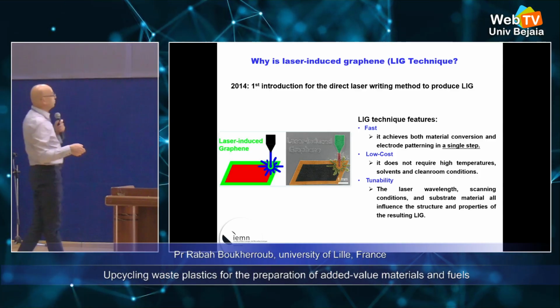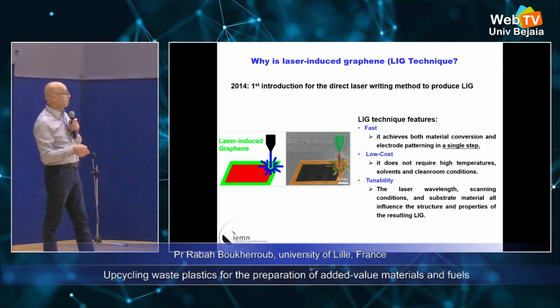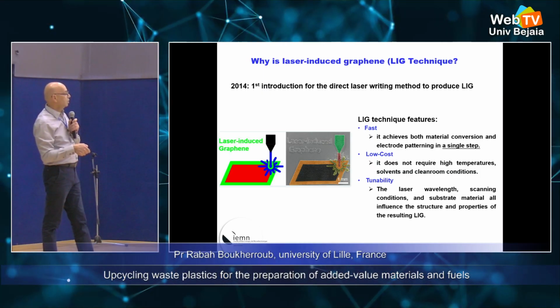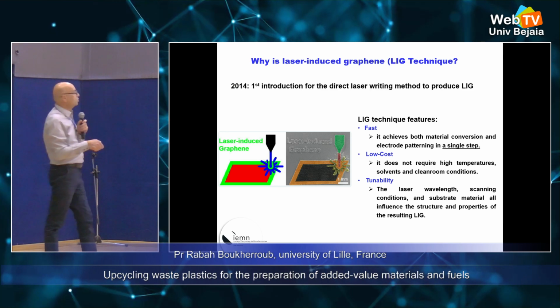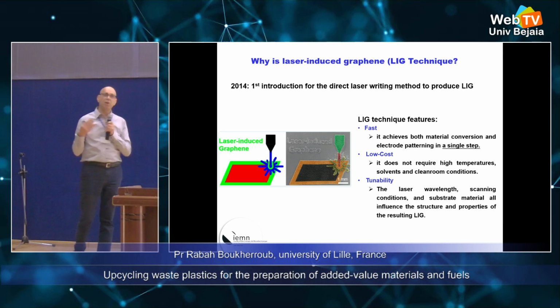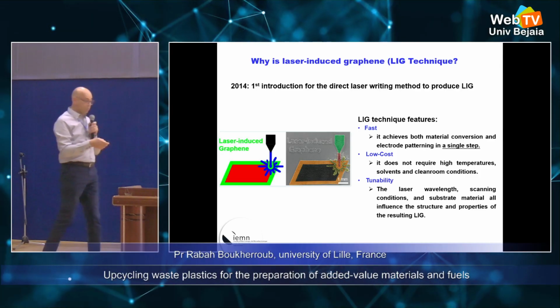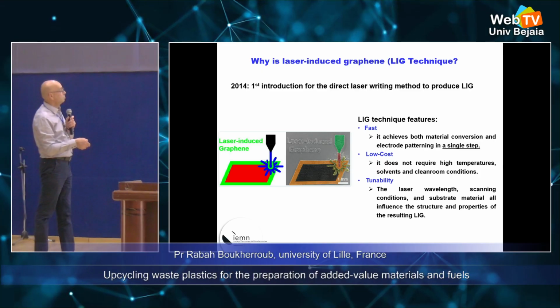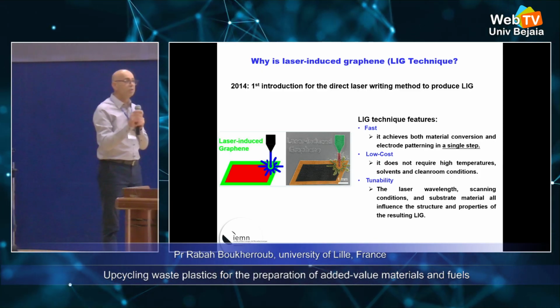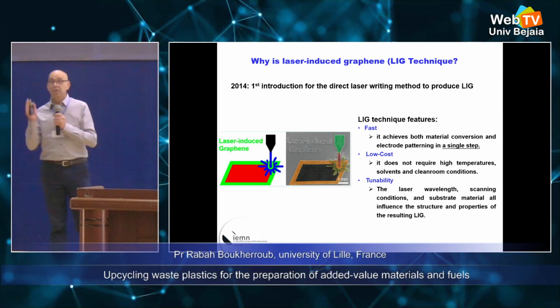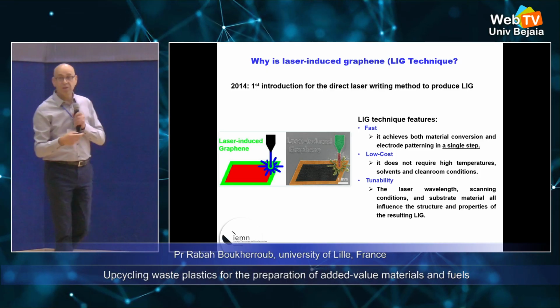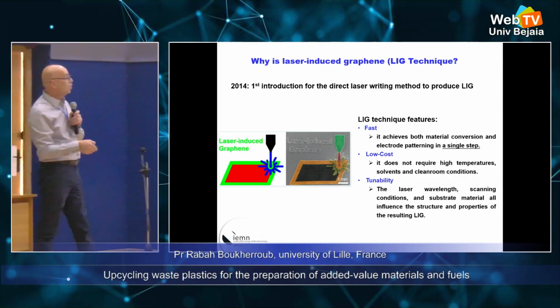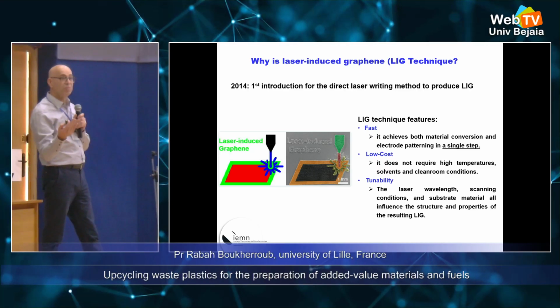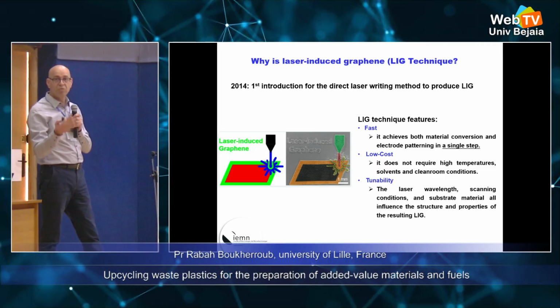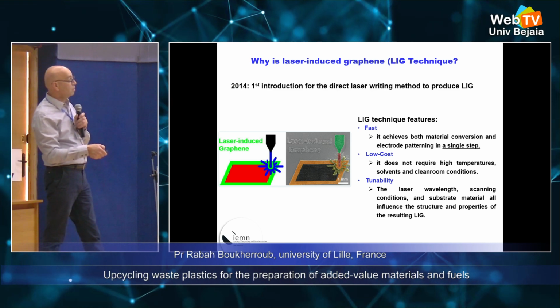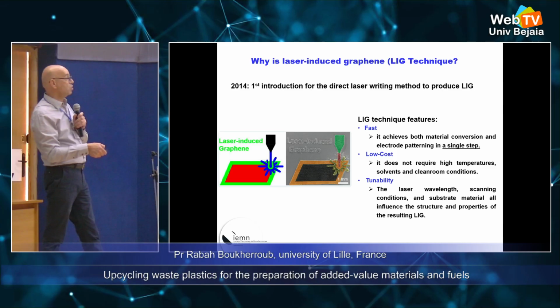So again, what we did previously, I said we used a laser-based light, LED, laser. Here now we use the CO2 laser. Why CO2 laser? Because it's much faster, you can write, but also you have much higher power. And with the CO2 laser, when I'm saying any polymer, it could be even a potato peel, I can transform that to graphene. It's so simple. If you have just a CO2 laser, you take any polymer, and specifically if you have waste, you can write graphene. So I can transform a polymer waste to a graphene-based or graphene-like material. It's quite fast. I can pattern in a single step. It's low cost. It's also tunable.